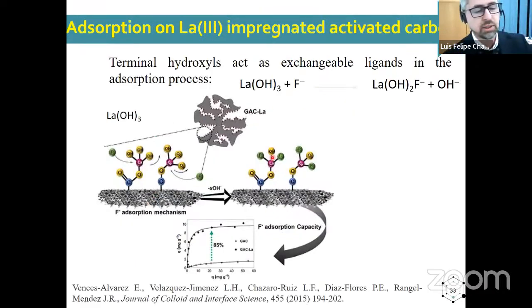In our group, and in collaboration with René Rangel, we have studied the adsorption process using granular activated carbon impregnated with hydroxyl lanthanum 3. And as you can see here, an abrupt increase was observed in the adsorption capacity and velocity of the commercial activated carbon F400 after its impregnation with lanthanum 3, because the presence of these hydroxyls is fundamental, since they can act as exchangeable ligands with the fluoride in the adsorption process. So it's a chemisorption. So even though the impregnation of lanthanum was optimized and the adsorption process performance was very good, it decreased when it was evaluated in tap water due to the competition with other anions.